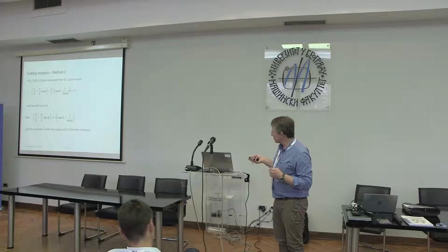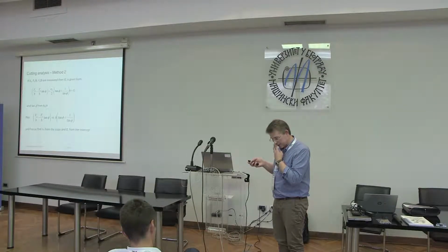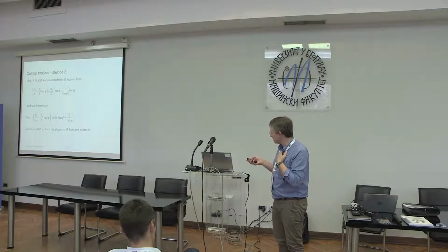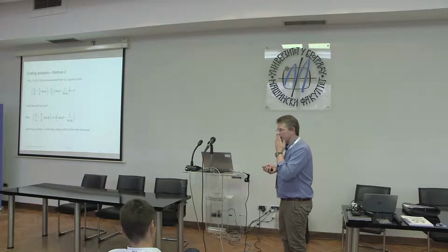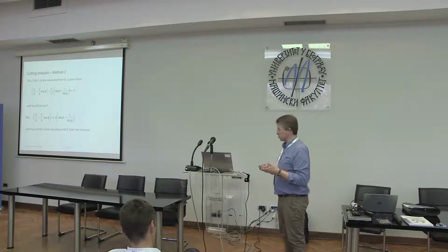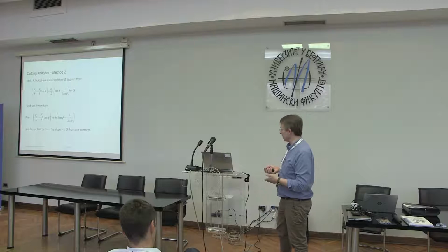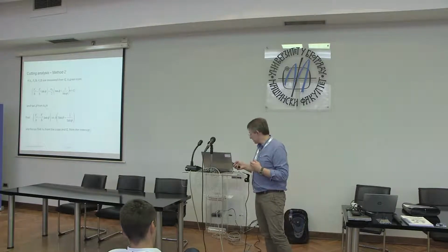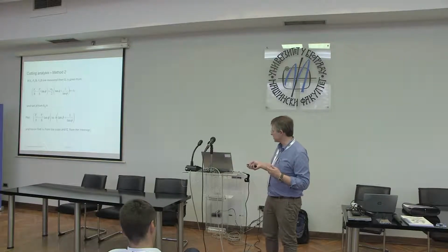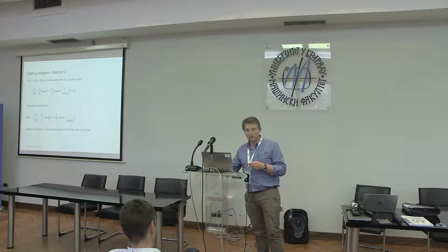So we've got different ways that we can approach this. So these are the analytical expressions. So these are either from this energy minimization or the ability to find the specimen and measure. But you can set up these equations from an energy analysis, which is how we did it. They do validate via equilibrium. And what we're trying to do is find the intercept of these plots to determine GC for the polymer. Now, another interesting thing is you can output the yield stress also from this analysis.